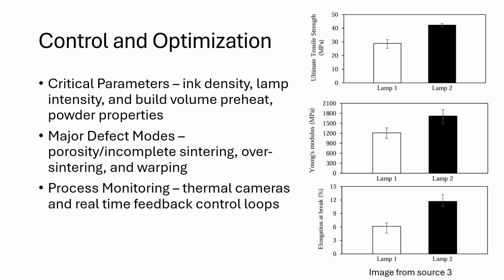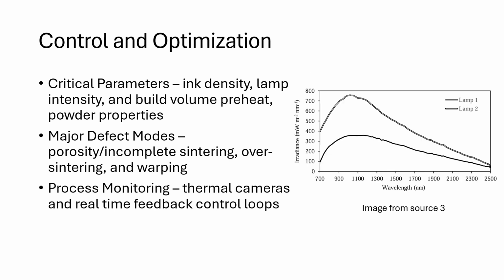Unsurprisingly, the increased density of the parts printed with the lamp that had the better coating also leads to stronger and stiffer printed parts, as shown by the testing that was done on the printed parts. Here we can actually see the emitted intensity of the two 2 kilowatt lamps that were used for the tests in the previous slides, with lamp 2 significantly outperforming lamp 1, peaking at approximately twice the irradiance.